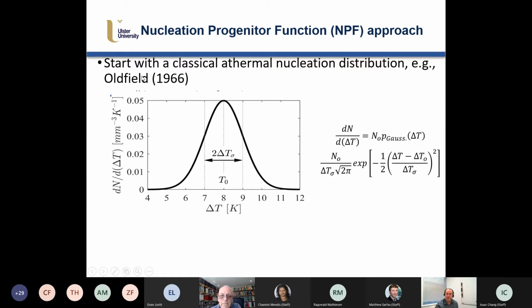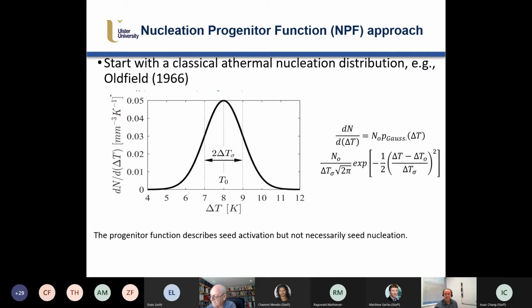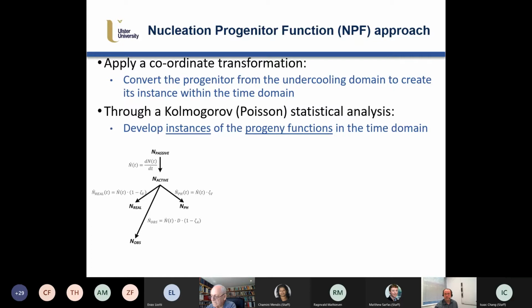Here we show one by Oldfield, which was 1966. This is a normal distribution. You can have a log normal distribution, and that might be closer to the work of Professor Greer and co-workers. You could have exponential. You could have a Dirac function, and that would be able to model explosive nucleation. But all of these, this is like plug and play. So you need a description of athermal nucleation, and we call this the progenitor function. The progenitor function describes seed activation, but not necessarily seed nucleation, or initiation, as we may call it.